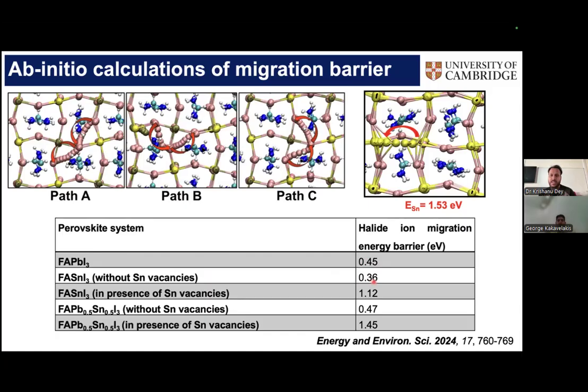So this can't really explain why, in the case of tin-based perovskites, the ion migration is becoming so much slower. But then we introduce some tin vacancies in the structure, and this seems to be the key. This increases the ion migration barrier significantly for both pure tin perovskites and mixed lead-tin perovskites. So it tells you that if you have some vacancies in the structure, this will create some local distortion in the lattice, and that will inhibit the long-range ion migration in these perovskites, which is where the ion migration barrier increases. And this explains well what we saw experimentally in the last few slides.